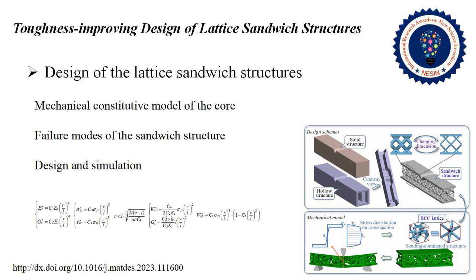Within a certain domain of the rod radius, the impact energy absorption of the sandwich structure decreases with decreasing rod radius, which means that the impact toughness declines gradually as the rod radius decreases. However, when the radius of the rod is reduced to a certain degree, the dimensional effect will arise. In this state, the impact toughness of the lattice sandwich structure increases significantly, with the synergy of the core and skins.